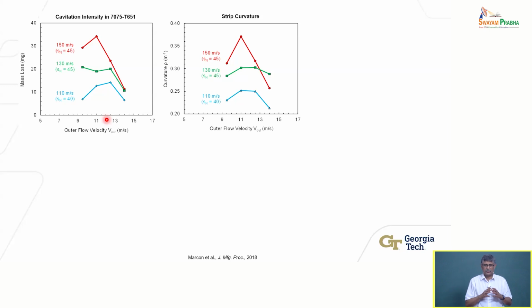And what will happen? If there are sufficient residual stresses you generate, then residual stresses will lead to distortion. Because what are residual stresses? They are stresses, elastic stresses in the body that will equilibrate, right? They'll adjust, and to adjust and make sure that the material doesn't break, it'll adjust its shape, okay? And you can show that from just basic elasticity theory, that's what happens. So you measure the curvature. The greater the curvature means more residual stresses in the material. That's simple to do. I can measure the geometry or the change in shape. This is what people will do in practice as well, okay?